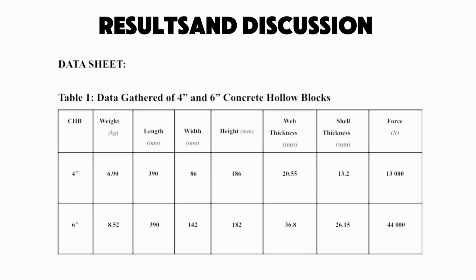Results and discussions. The 4 inches CHB shell thickness of 13.2 mm falls short of the ASTM C90-23 standard requirement of 19 mm. Nevertheless, its web thickness of 20.55 mm satisfies the ASTM C90-23 standard, which called for a minimum web thickness of 19 mm. The 4-inch CHB satisfies the ASTM C129-23 standard, which called for a minimum shell and web thickness of 13 mm.